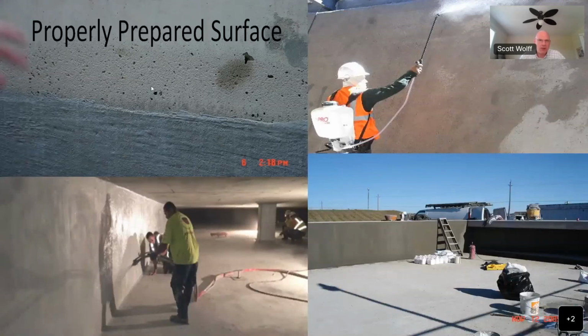And again, we talked about a properly prepared surface. This is an example in the upper left-hand corner of a CSP3. It does require high pressure water to achieve this. Mechanical abrading, interestingly, is not generally acceptable to the manufacturers. So, if it's a pre-existing building and it's below grade and it doesn't affect the interior occupants in other areas of the building, this might be a possibility. But this is something I always bring up early on if somebody's considering this: this high pressure water opening up of the concrete to receive the crystalline.